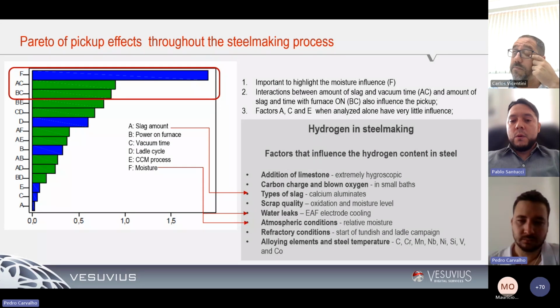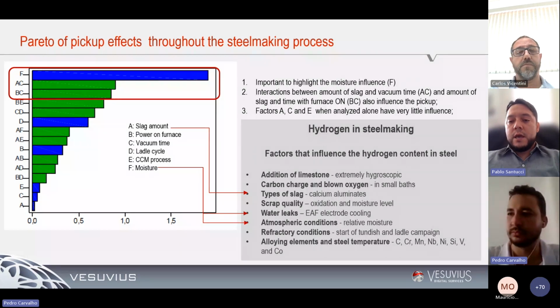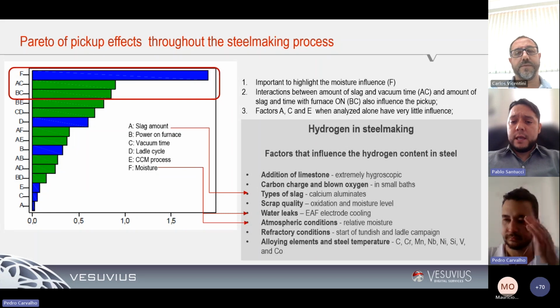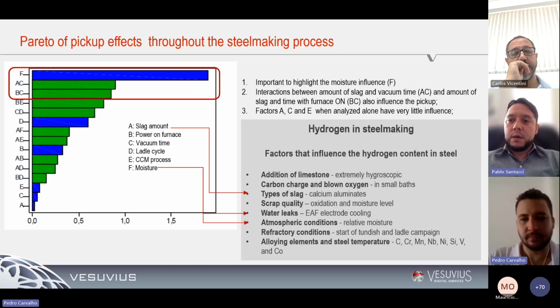Not only that, but water leaks, for example in the EAF stations, can also contribute to this pickup of hydrogen inside of the steel. And there are some other factors that can also contribute to this pickup, like the type of slag, or depending on the carbon charge or alloy that has been put inside of the steel during this process. Next slide, please.